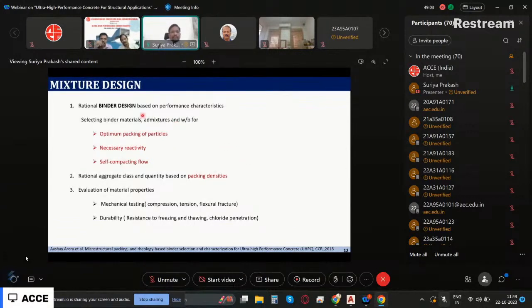Now let's see how the mix design is done. A rational binder design or mix design is based on the characteristics. I first have to target the optimum packing that I can achieve from the size of the material, and how reactive all these materials are. I should also retain this self-compacting flow so that it can flow on its own. And we also need to determine the aggregate class and quantity required based on the packing density that I'm trying to achieve. Now, how do we evaluate the material properties of all the raw materials? Of course, we need to do mechanical testing: compression, tension, flexure, fracture. And because this is a very highly durable concrete, it should also satisfy some durability performance: chloride penetration, resistance to freezing and thawing, and so on.